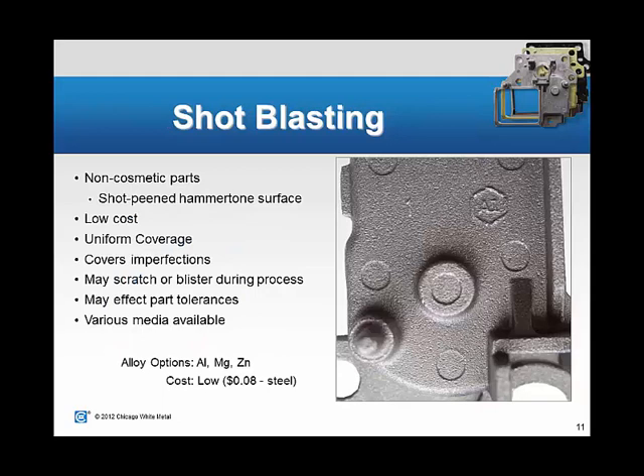So here's the first example of a type of mechanical finish, shot blasting. The part pictured here was performed in the Wheelabrator process, which should be familiar to a lot of people. It was done with a steel shot, and because this part was aluminum, we can do that. We wouldn't recommend steel shot for magnesium or zinc alloys, but this is what we did for aluminum.